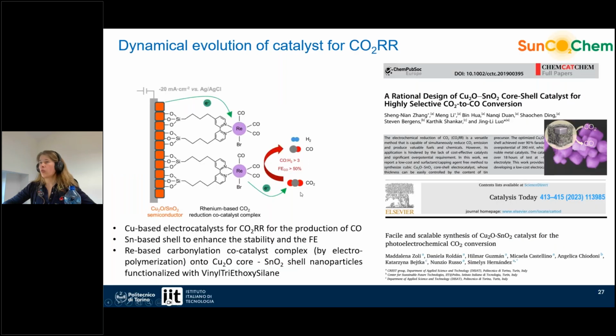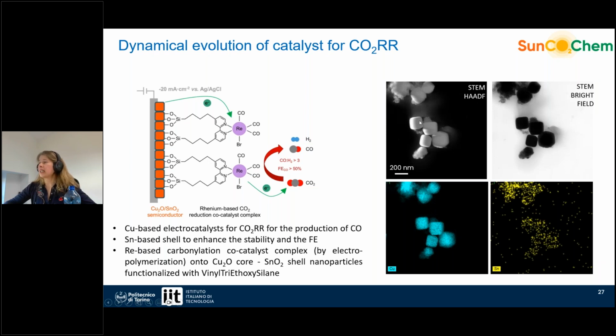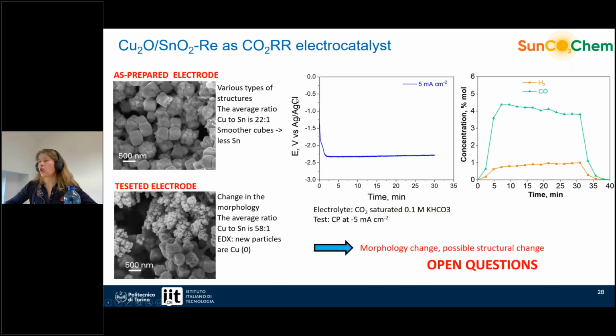The next example, which I want to show, is the dynamical evolution of the catalyst for CO2 reduction reaction. So we are interested in the framework of the project to study the copper-based electrocatalyst for CO2 reduction to produce carbon monoxide. And this copper-based catalyst is actually a catalyst in the form of cubes with a SnO2 shell, which should enhance its stability and Faraday efficiency.